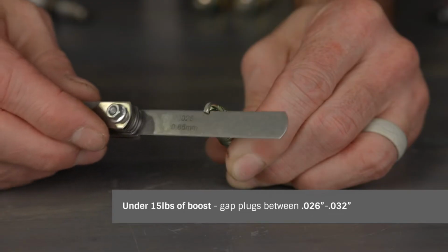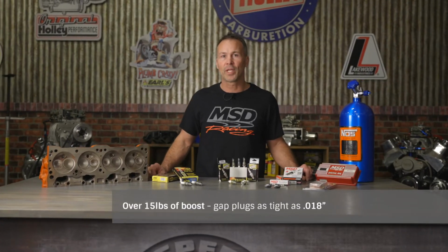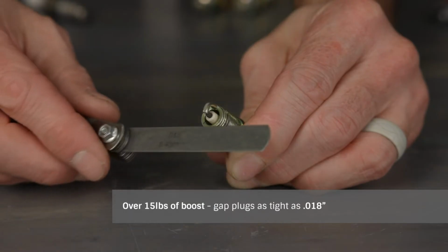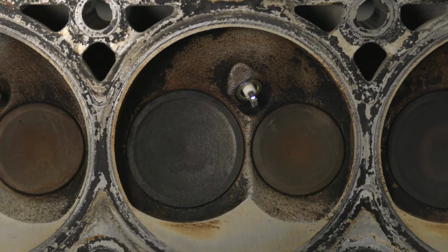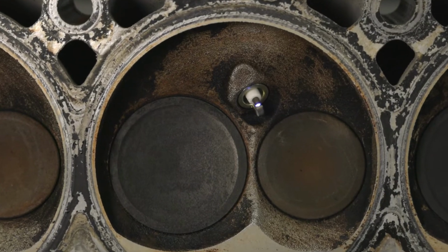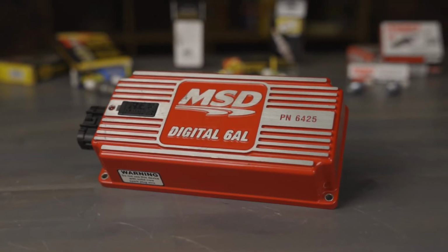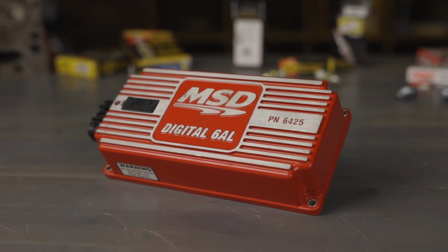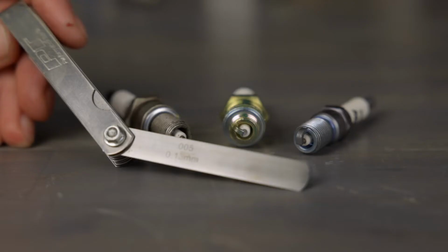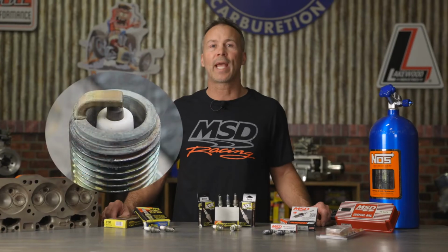For applications with less than 15 pounds of boost, gap your plugs between 26 and 32 thousandths. For engines with over 15 pounds of boost, you may need to gap your plugs as tight as 18 thousandths to prevent breakup. A good rule of thumb is to decrease the spark plug gap in 5 thousandths increments until you obtain a stable idle RPM and you don't experience any breakup under full boost. Ignition systems that provide a hotter than stock spark can benefit from a larger plug gap. Plug gaps should be increased slowly in 5 thousandths increments until you have a nice smooth running engine with a tannish color porcelain.